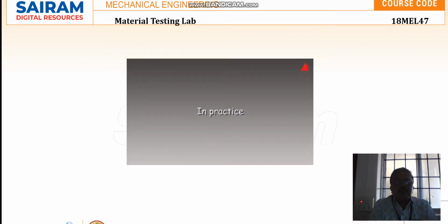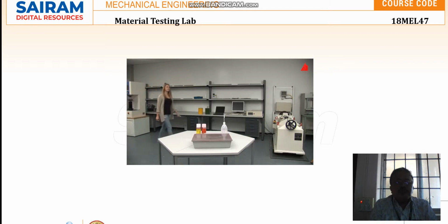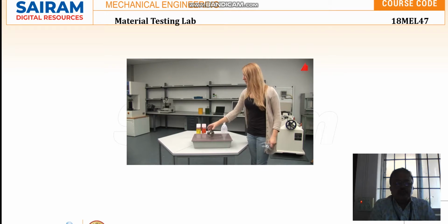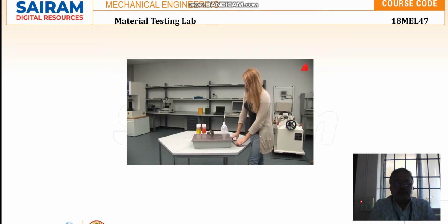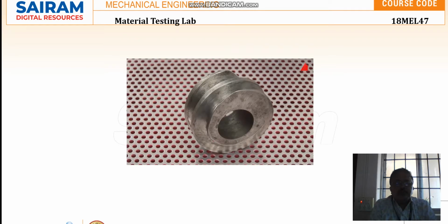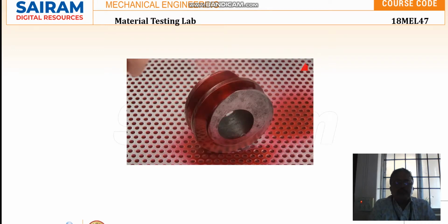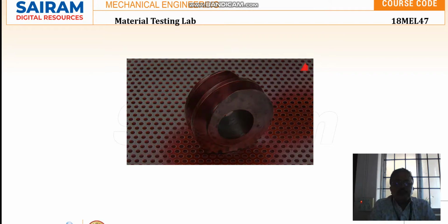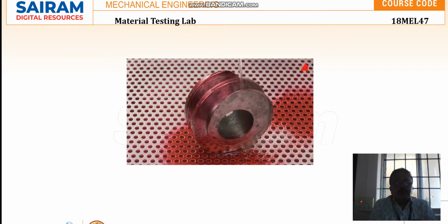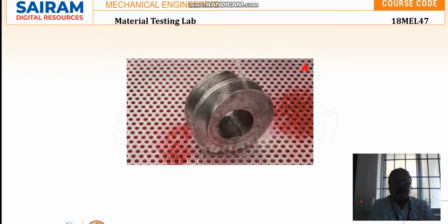And this is how it is carried out in practice. We wish to inspect two samples, a segment of a worm gear shaft and a broken bicycle crank arm. Both test pieces have already been cleaned. First in line is the worm gear shaft. The material tester applies the penetrant. After a dwell time of about 10 minutes, she removes the excess penetrant from the surface by rinsing the test piece gently with water. She takes care not to rinse for an unnecessarily long time because the penetrant is supposed to stay in the defects.